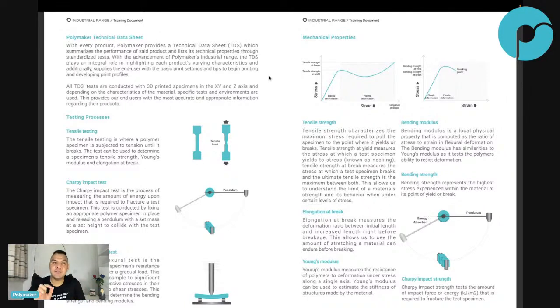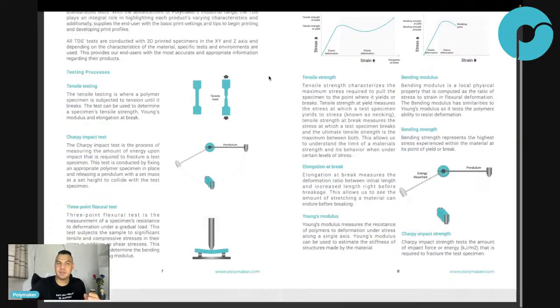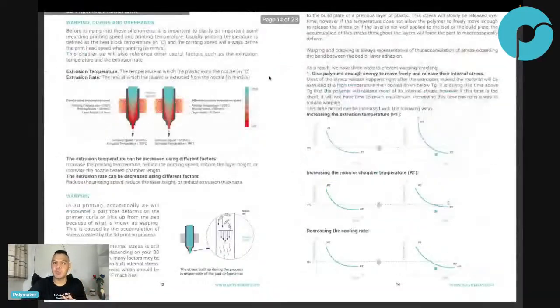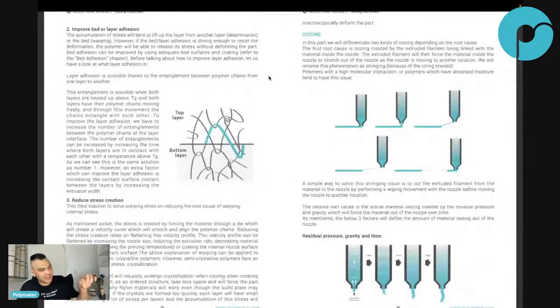So what does that mean? It means crystallization induces shrinkage. If you have something that crystallizes, it shrinks. Okay, you get where I'm going now? We're talking about shrinkage, talking about warping. So that's happening if you print nylon and each individual layer starts to crystallize, and then it shrinks more and more, and then you add all of these layers that are shrinking because they crystallize, and then it's warping. And that's why nylon, PP, PEEK are very hard to print. These semi-crystalline materials, because of the crystallization process.